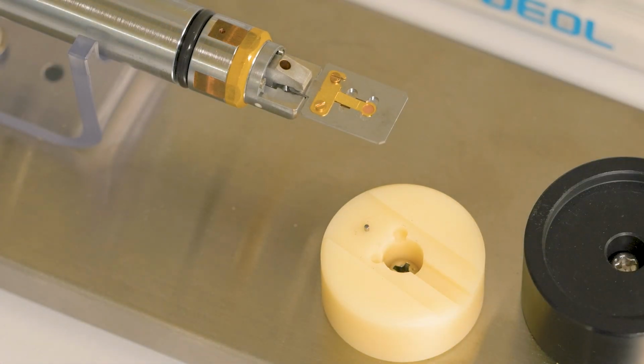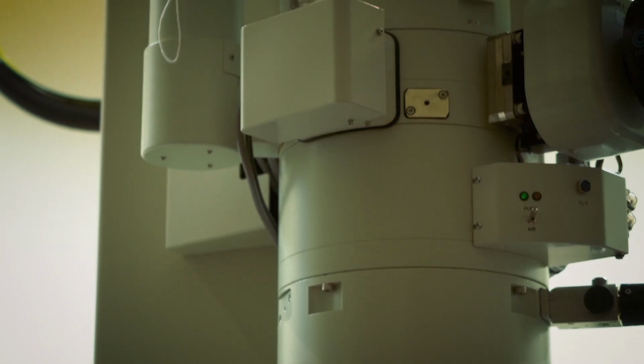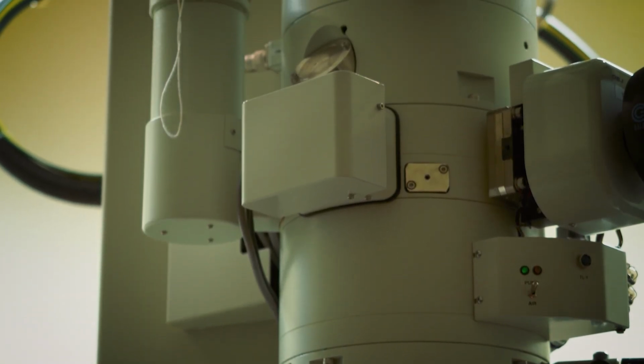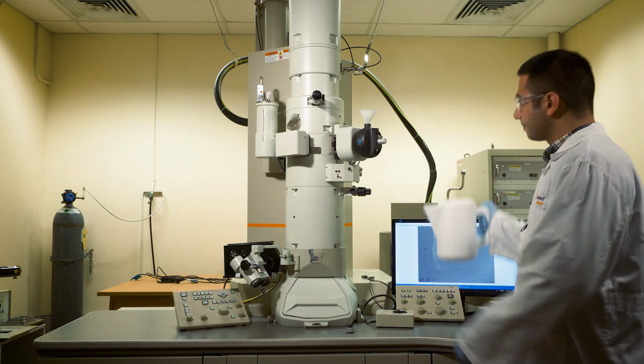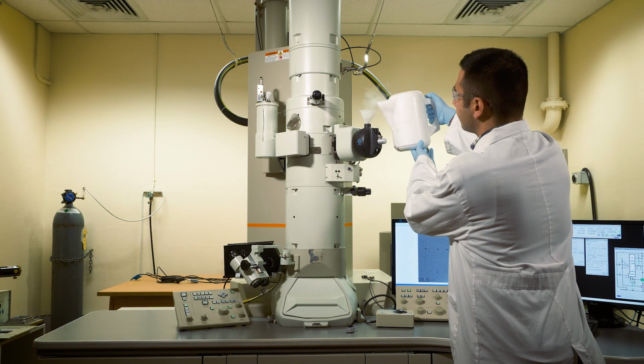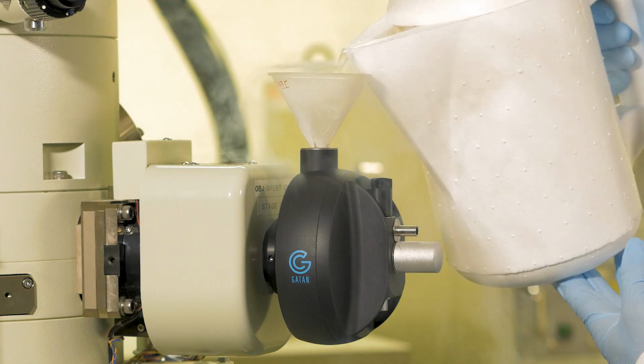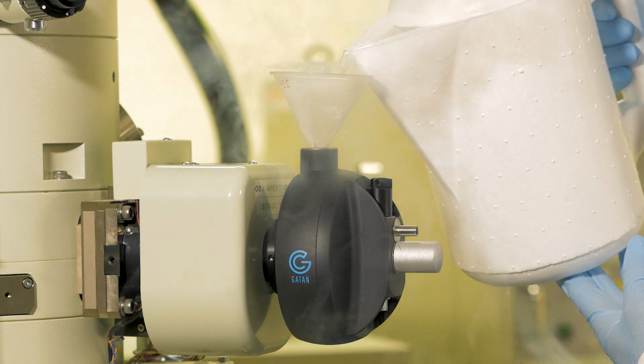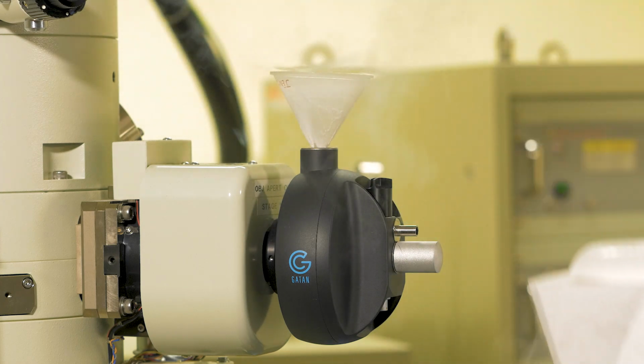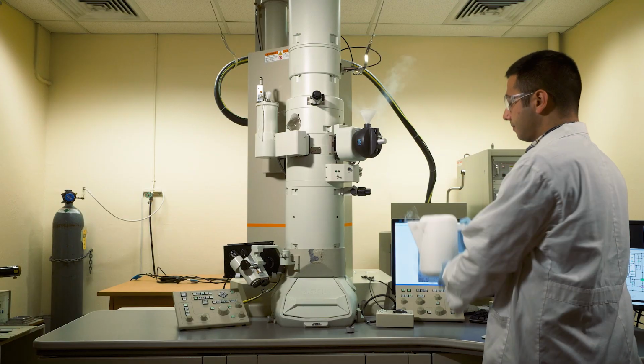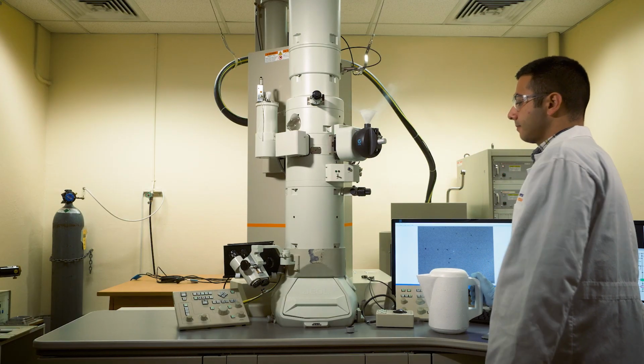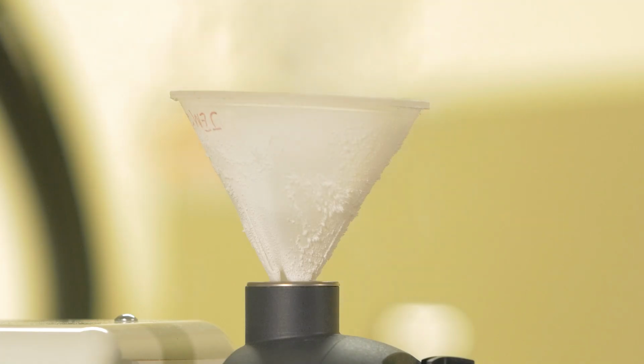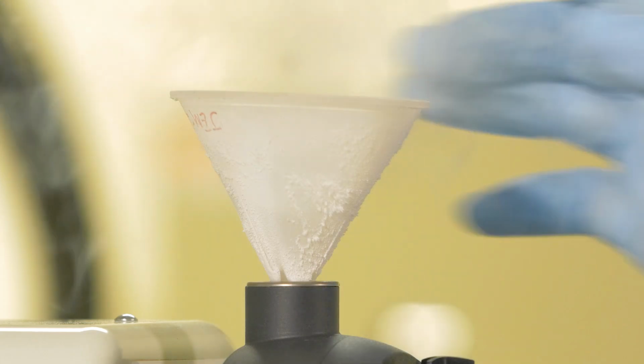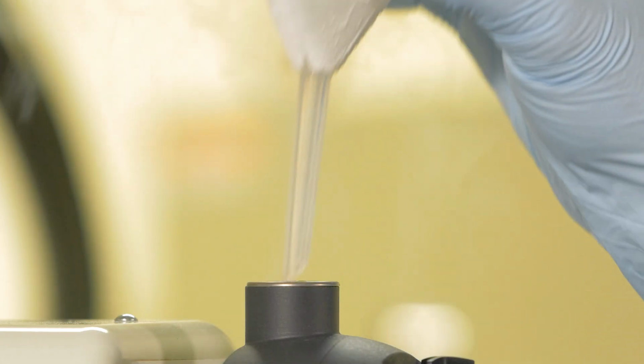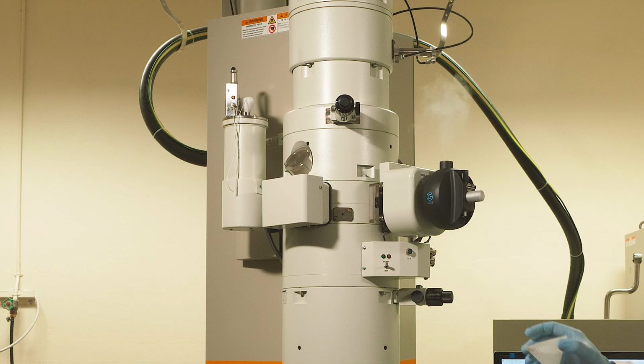Then the sample is placed in the TEM machine and we wait to pump down and achieve the proper pressure and vacuum. We need to fill the sample holder with liquid nitrogen, which helps minimize contamination and improve the vacuum and recovery time from specimen insertion. Also, freezing the samples prevents them from evaporating in the vacuum of the electron microscope. In addition, the low temperature will also protect the sample from damaging interactions with electrons used to image the sample.